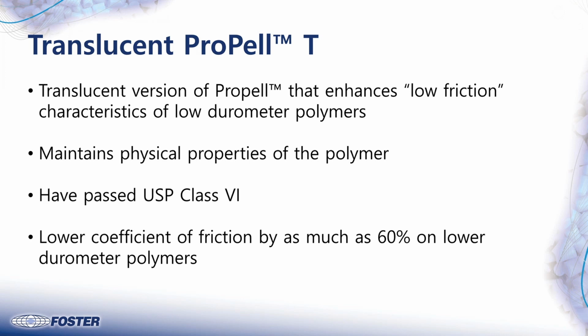So you'll see some of the softer nylons, 12, 11, but you're starting to get into the polyurethanes and the polyether block amides, which go all the way down to about a 75A, 25D durometer. So you like to have the ductility of the soft, but you also need the rigidity and the torqueability of one of these rigids. Well, those are competing ideas. So what are some of the ways of getting around it?